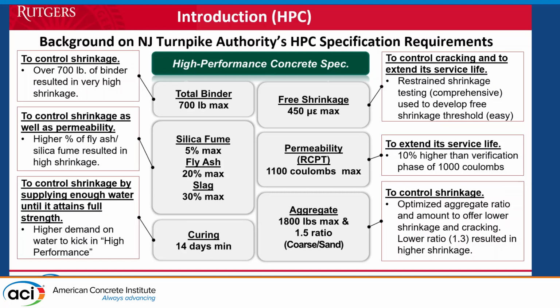So for this, we developed a specification, and unlike other states, we added the shrinkage limit to that by using the free shrinkage, but it was based on a study that we did for restrained shrinkage conditions, and we also included the blended aggregate as part of the mix design itself.